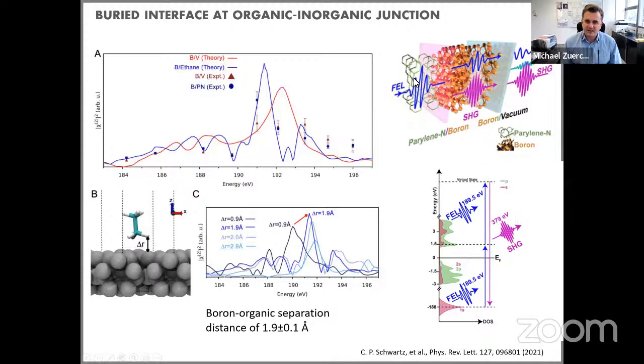And the way one thinks of this experiment is that the FEL impinges. Parylene is not going to do much, it's largely transparent, it's a very thin layer. The FEL then impinges on the boron-parylene interface and generates second harmonic at this interface, where the symmetry is broken. Then boron absorbs quite a bit since we are resonant with the 1s state. So the absorption of boron reduces the intensity sufficiently that on this second interface, boron to vacuum, we don't expect much second harmonic to be added. You basically absorb a large percentage of your incoming FEL beam within the boron slab.